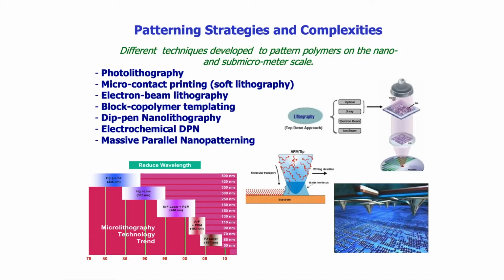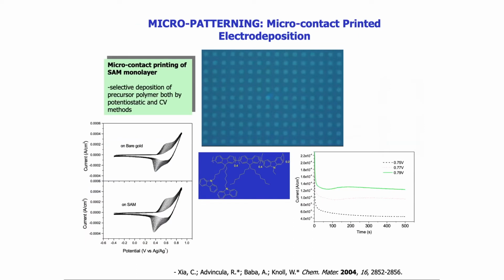Certainly, AFM plays a very important role because this allows us to use, let's say, a cantilever tip or conducting AFM to deliver the molecules, or in our case, to actually pattern the oxidation or electropolymerization of the material. So we first noticed this phenomenon in microstructured patterns, let's say these self-assembled monolayer dot patterns, where we actually formed micro LEDs based on the patterning of a carbazole modified polyfluorene, as shown here, where we electropolymerize the polymer, or precursor polymer rather, on the dot structures, resulting in these micro LEDs and IV performance.